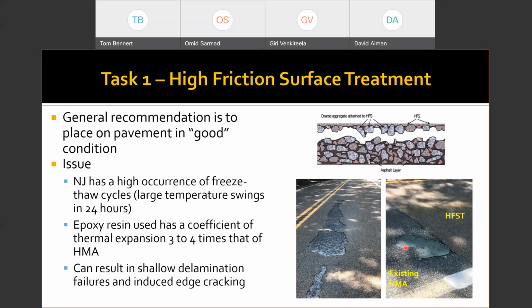We can pave a brand new road tomorrow, but we can make that asphalt to a condition where it feels very old. So the problem we get into is, what is good? And when we don't know what is good, we get into some of the distresses that you see below. This is what we call a shallow delamination. What happens here is that the epoxy surface on the top with that resin essentially shears and rips off the top half inch of the asphalt pavement. And in doing so, you're left with what looks almost like a very shallow type of pothole.